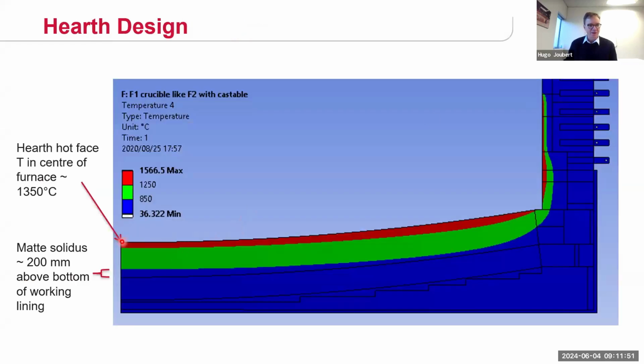Also on the hearth design, what we did is we designed it to maintain the matte solidus temperature isotherm above the bottom of your working lining. That is the bottom of the working lining, and that matte solidus isotherm we estimated would be 200 millimeters above that. The reason for that is if you do get matte penetration in the hearth, to make sure it will freeze before it gets to the bottom of your working lining.